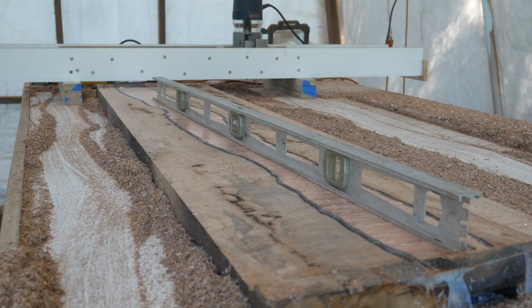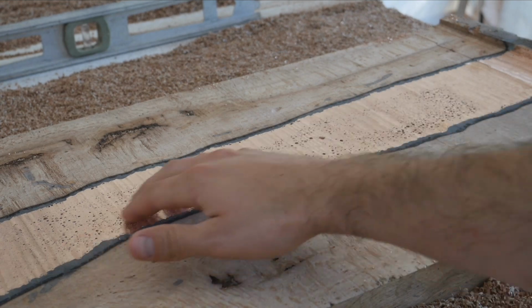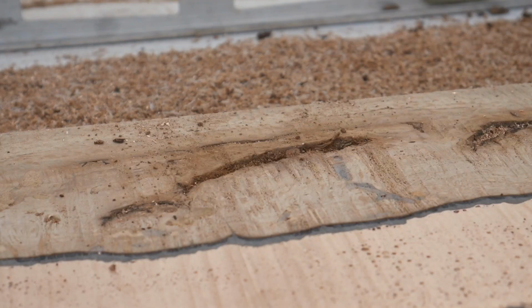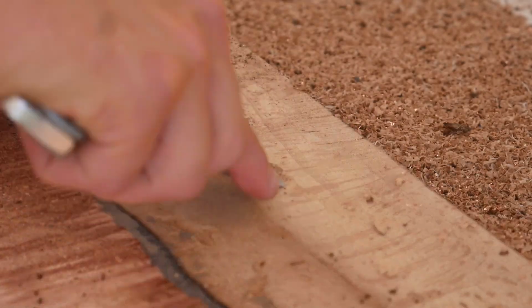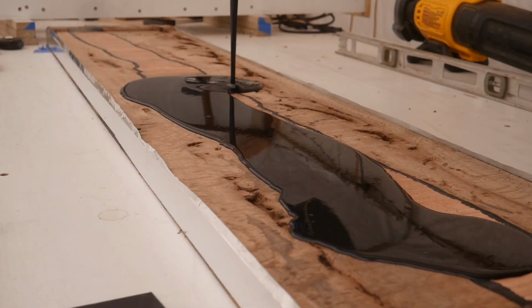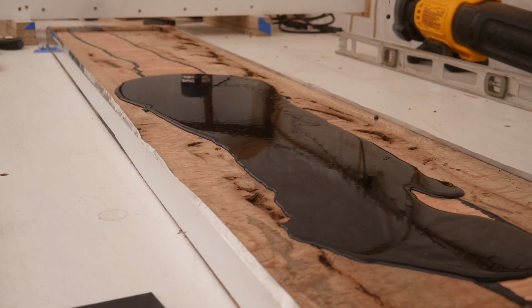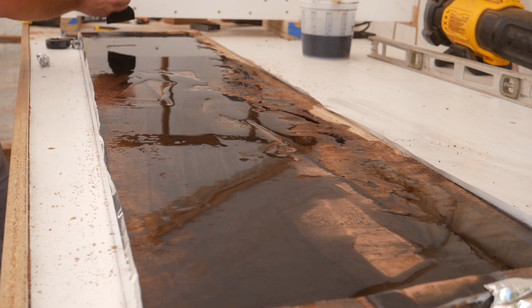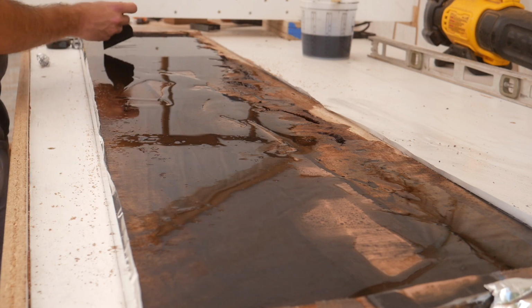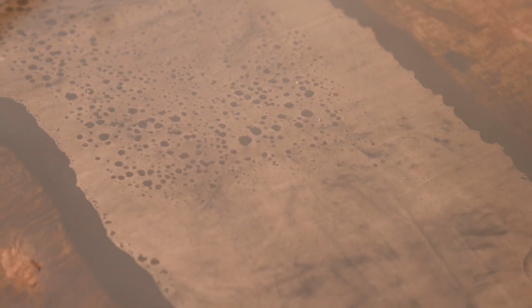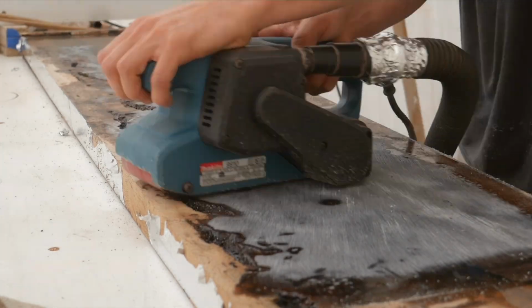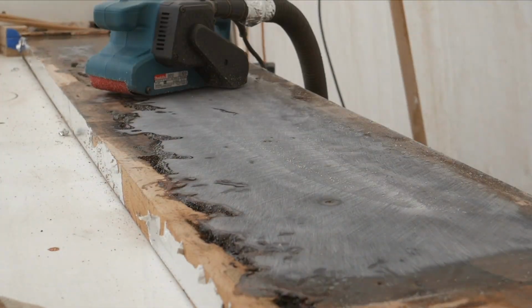Milling the bronze down did open up some small holes throughout the bronze, so I decided to carve out any rot on the slabs and do a thin flood coat of resin over the whole tabletop to fill any holes in the slabs as well as any holes in the bronze. I thought about brazing in some bronze into the holes on the river, but the heat created in brazing would likely heat up the river to the point where it could potentially delaminate from the slabs.